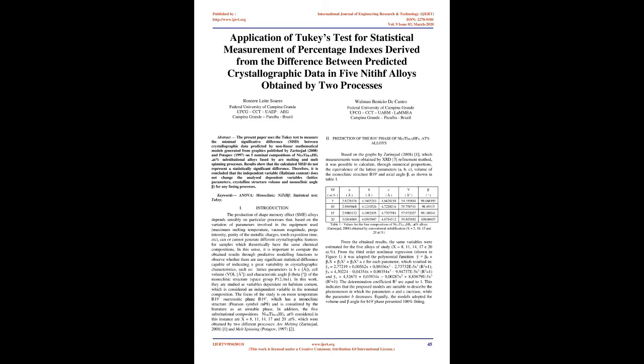Results show that the calculated MSD do not represent a statistically significant difference. Therefore, it is concluded that the independent variable, hafnium content, does not change the analyzed dependent variables, lattice parameters, crystalline structure volume and monoclinic angle β, for any fusing processes. Keywords: ANOVA, monoclinic, NiTiHf, statistical test, Tukey.